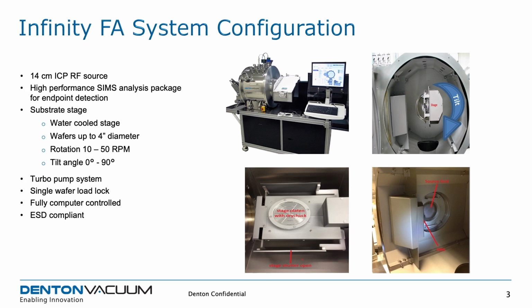It takes wafers up to 100 millimeters, although typically you're just mounting a single piece in the center. Has rotation from 10 to 50 RPM, and the tilt angle goes fully from 0 degrees, which is facing the source, to 90 degrees, fully perpendicular to the source. And I'll show later why that's important in order to control the selectivity and get a planar etch across the whole chip. So the tool is turbo pumped, which means it can be compatible with reactive and corrosive gases instead of the usual argon, and it has a single wafer load lock. And the whole tool has full computer automation, including recipes that use the SIMS for endpointing.